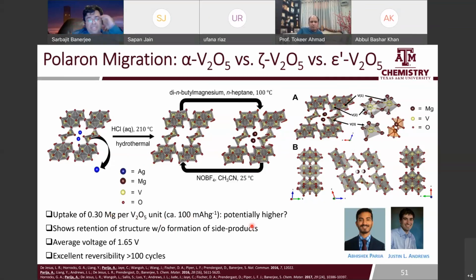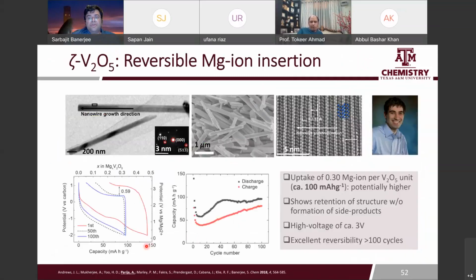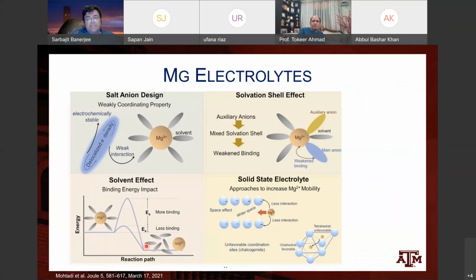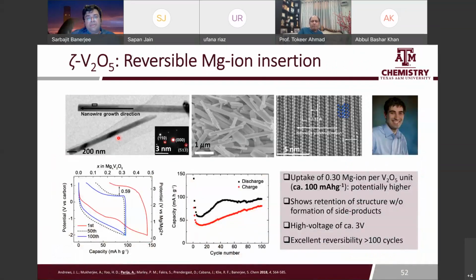We can go a little bit higher even at high temperatures, and then we can retain the structure and have an average voltage of 1.65 volts, much better than what you saw with the Chevrel phases, and very good reversibility over 100 cycles. Okay, so reasonably good reversibility, and we retain the structure for over 100 cycles. So this is probably still one of the best performing high voltage, high capacity cathode materials that exist right now.